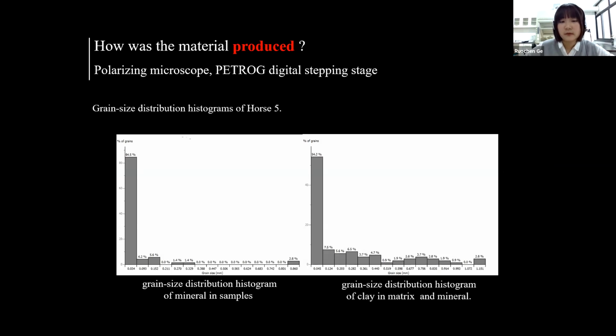For further study of the source of this material, grain size analysis was performed. This figure shows the mineral counting with one major peak in grain size, which is similar to the grain size distribution in potteries. Due to the grading of the material by weathering, whether water or wind, unimodal grain size distribution always occurs in natural clay. However, when the mineral and clay grains in the matrix were counted at the same time, some mineral peaks appear because the clay and the mineral in the original pottery materials experience the same degree of weathering. Their particle size distributions should be the same.